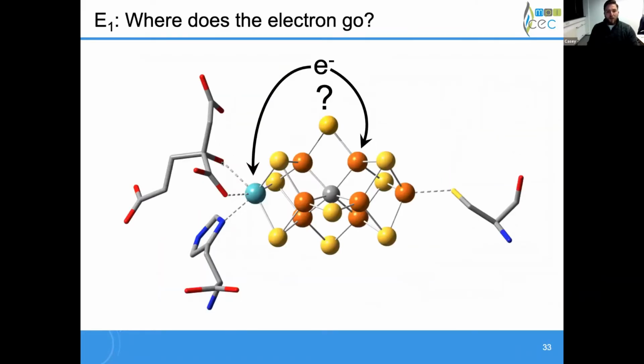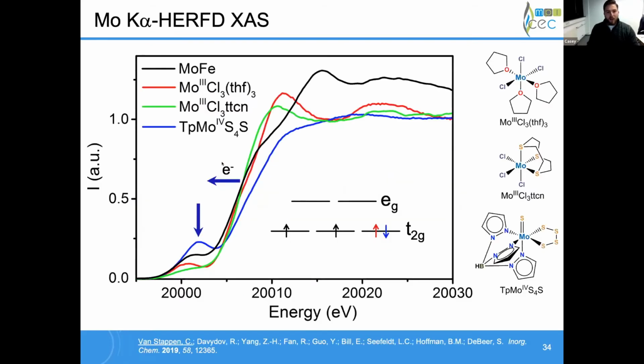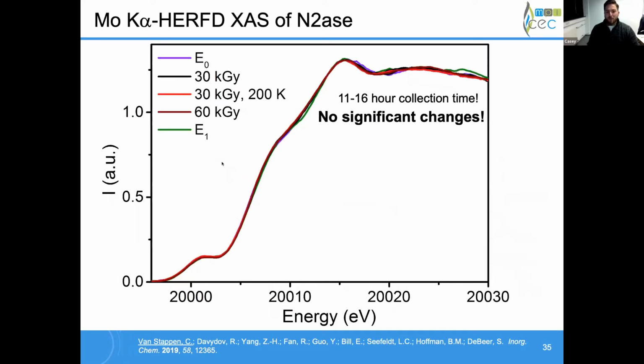And so with that, let's go back to the question of where the electron goes, now that we have a little bit of background of how at least I'm thinking about these experiments. If we want to ask what happens at molybdenum when we have reduction, usually it's good to have a couple model complexes to demonstrate what might happen. If we look at going from molybdenum 4 to molybdenum 3, we have a diagnostic 1 electron shift in the edge. And that's really our biggest indicator for reduction at molybdenum. And since we only have one unique molybdenum in nitrogenase, we would expect to have something of a similar magnitude if we have a 1 electron reduction in the FeMoco cluster. And what we see is absolutely nothing.